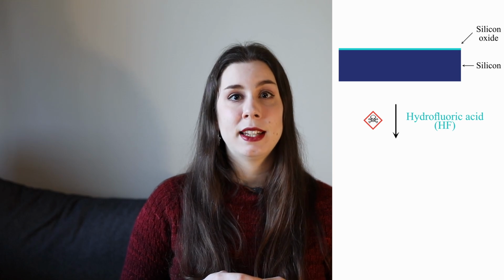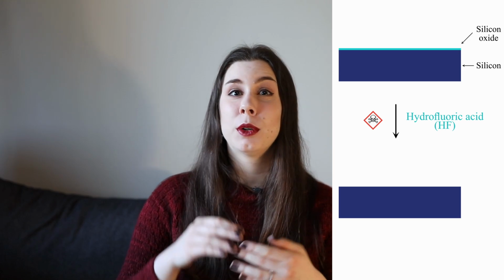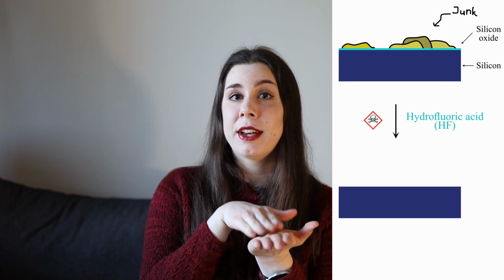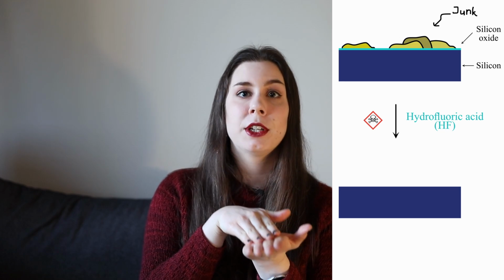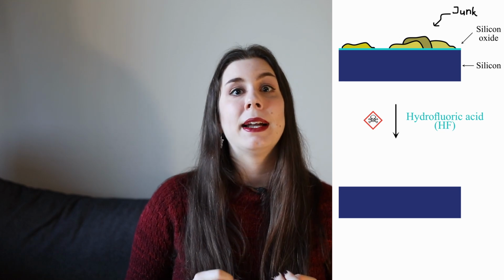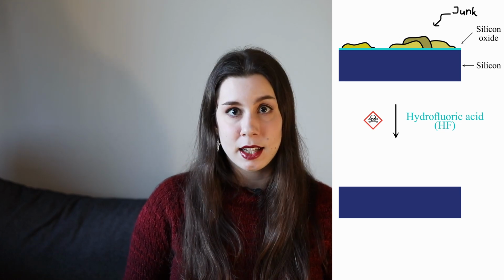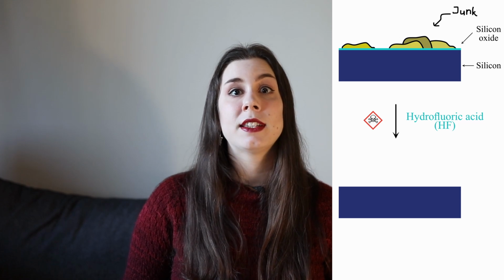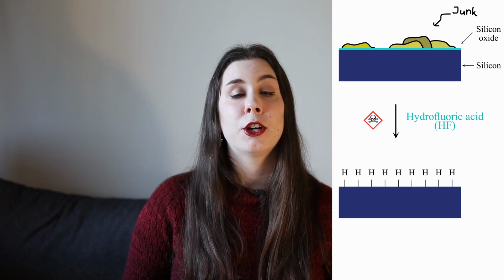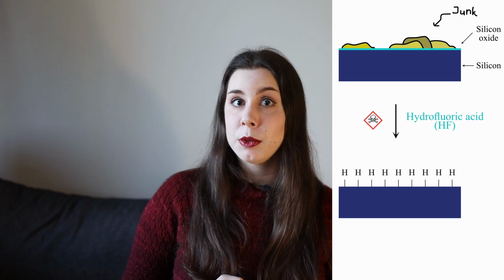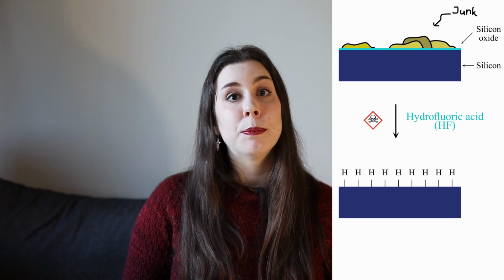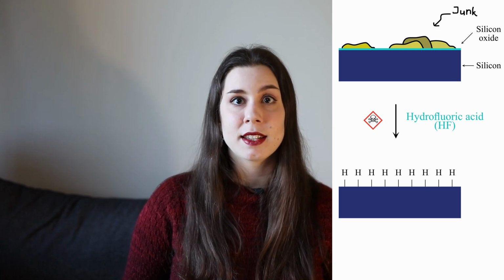HF will remove the silicon oxide, and with it hopefully also lift off any kind of junk that may have accumulated on the wafer surface before it got to our loving care. But it will not damage the underlying silicon. Instead, it will leave the silicon passivated with a single layer of hydrogen that, as an added bonus, will repel water and temporarily prevent the silicon from reoxidizing.